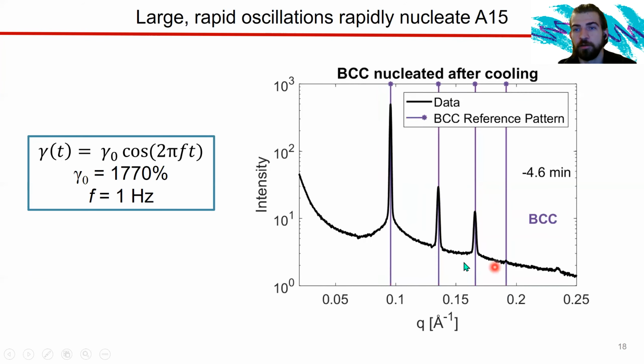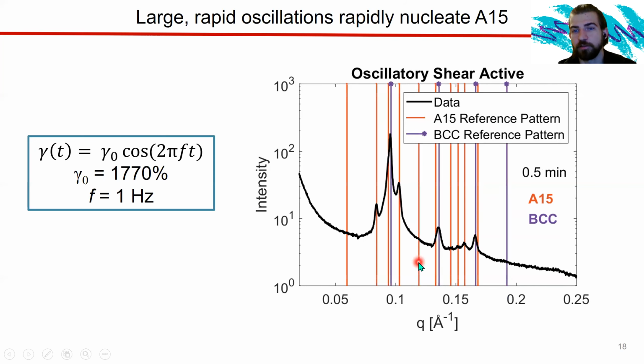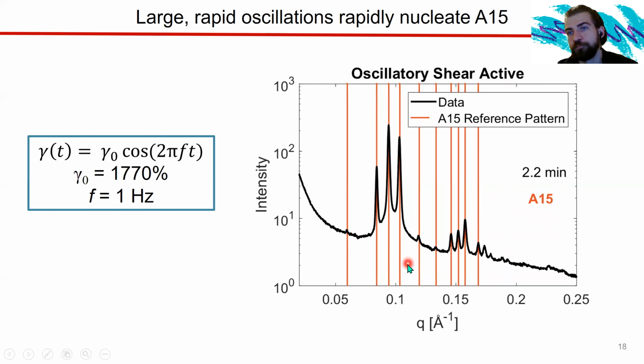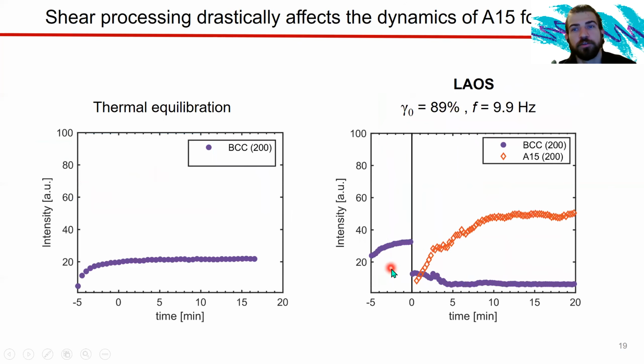And now, okay, we're back to the start of the GIF. We're at BCC. We're going to start oscillations now. And the A15 phase comes screaming in. Now that's a pretty big find. You can see that when we plot this as intensity versus time, you have thermal equilibration alone on the left, and you have shear processing on the right that starts here at 0. And you can see that BCC drops dramatically and A15 comes in.